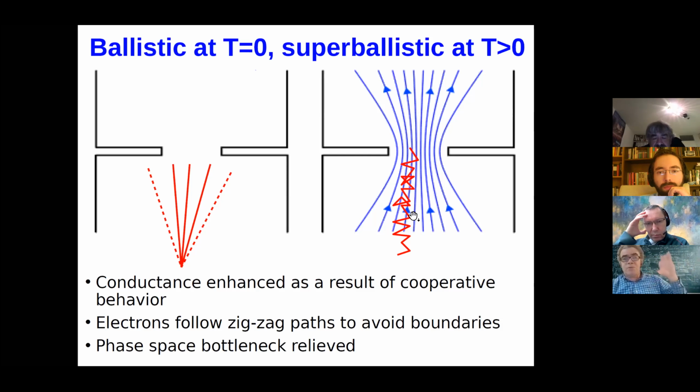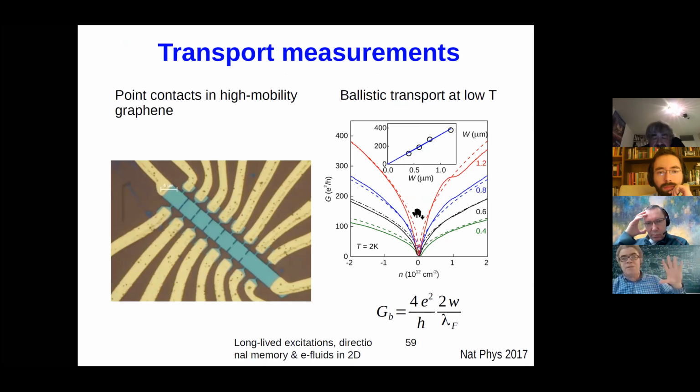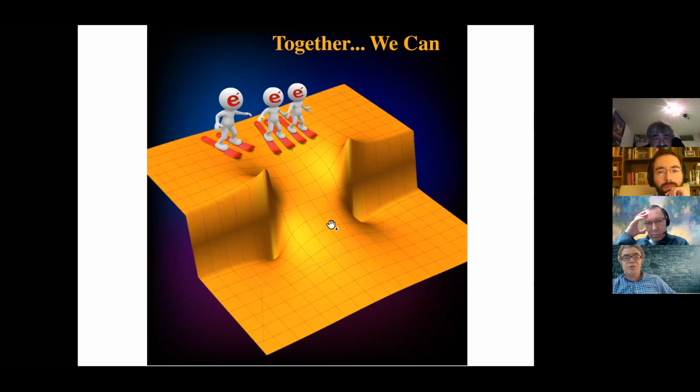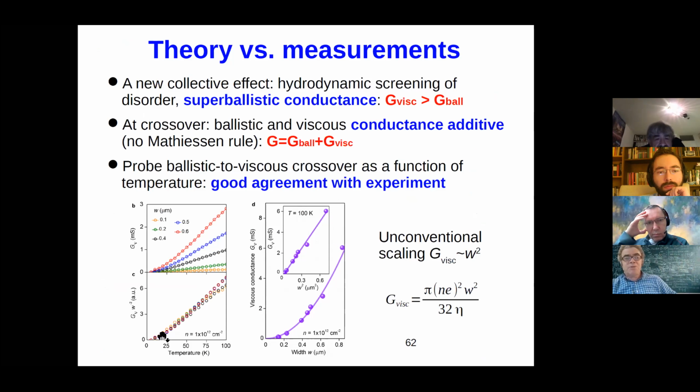But also, as part of that study that mapped it all out and showed that indeed resistance drops when you increase temperature, the temperature dependence of conductance of that constriction is not what you expect based on a conventional Fermi liquid. It looks to me like pretty much a linear temperature dependence, up to a temperature where something else happens and phonons kick in.